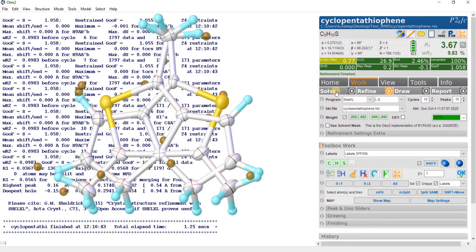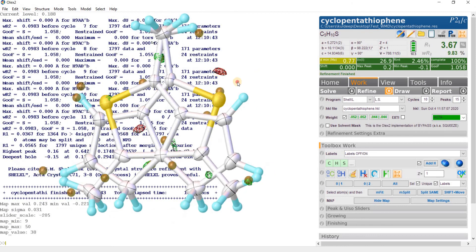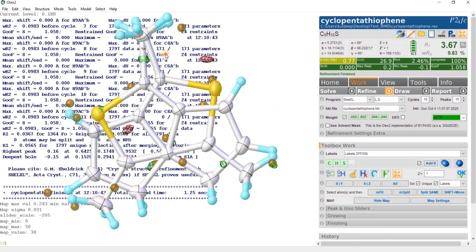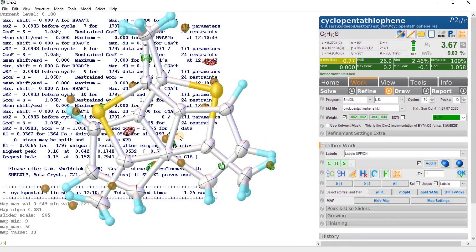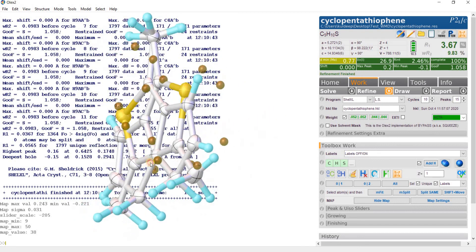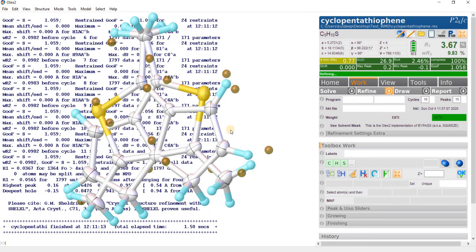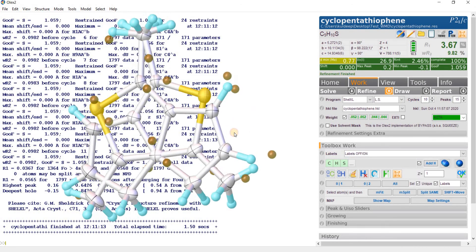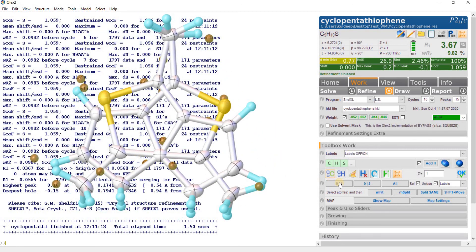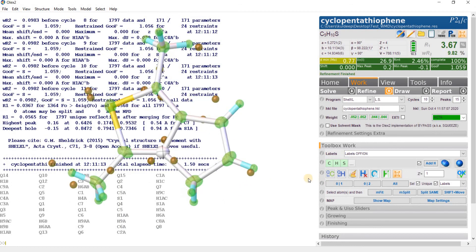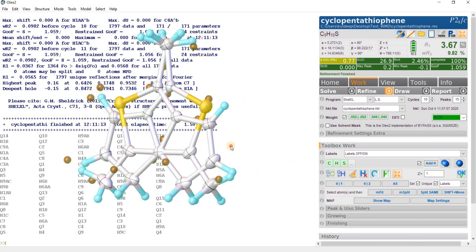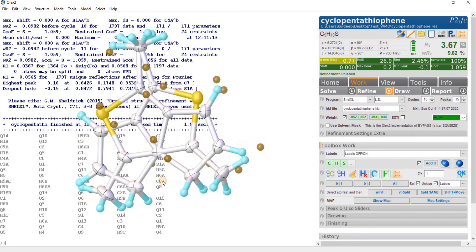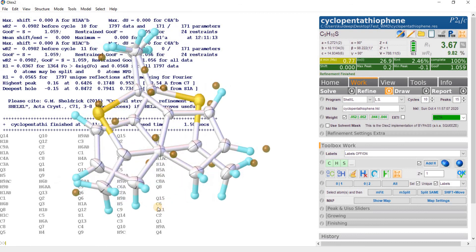For that, type edit, add SHEL command with 999 meaning infinity and 0.76. Save and refine. Refine one more time. Now everything is settled down, everything is green. Let's look at the electron density map, press Control+M. Now you can see there is hardly any electron density left. So just give a final refinement. Now the whole thing is settled. There are two parts. Press 01 to see part 1, and 02 for part 2. For whole, you will see the full disorder. Now the structure is solved. Finally, thanks for watching this video.